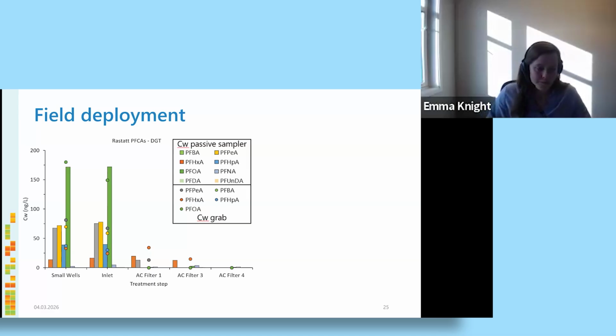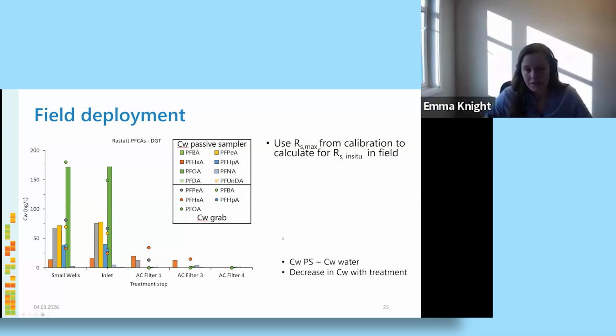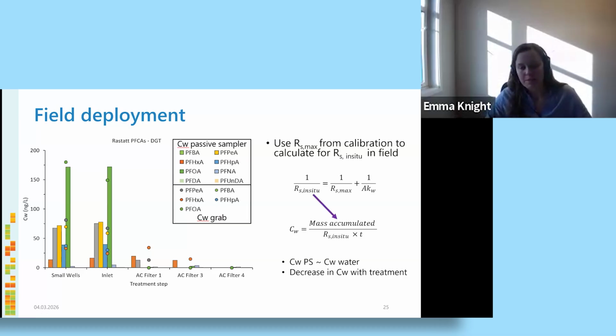So the dots and the bars, they match up very, very nicely. And this is fantastic, because then we can show that our passive sampler is working how we hope that it should be working. And very briefly, we can use this calculation from the calibration to then calculate, that's how we've calculated our concentration in the water from the mass accumulated.